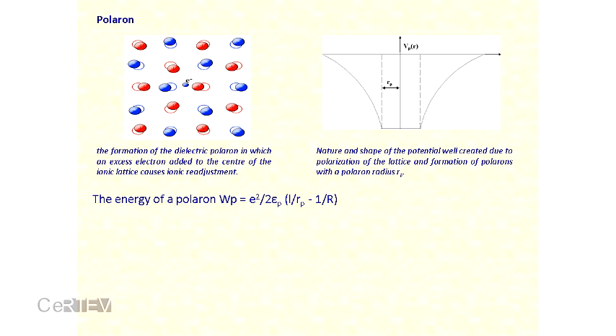To take a quick view of polarons, I am trying to make you understand in the simplest way what a polaron is. If you have an ionic crystal, and you make an electron pass through it, you can see that due to the interaction of the ions and the electron, the ion positions are distorted. Because of this distortion, it costs some energy, so the electron is confined in the distortion field, and it cannot move very fast. So it becomes heavy, and this heavy electron is called a polaron, because it is associated with this deformation field. You can also explain it as a potential landscape. You can see the polarization of the lattice and the formation of the polaron. This polaron is of course distributed over a specific region, and that is called the radius of the polaron or the dimension of the polaron.